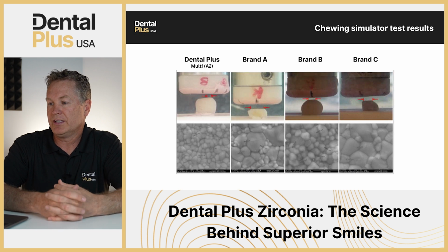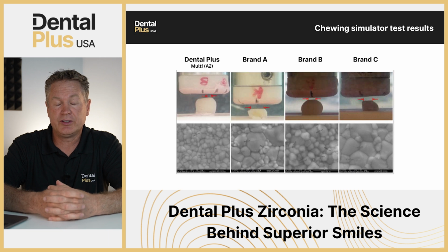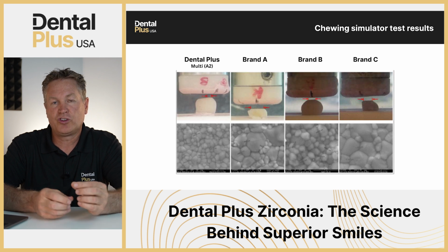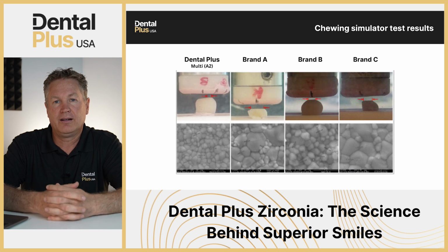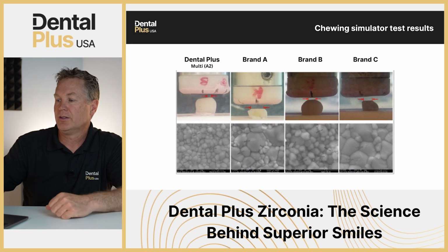So you'll notice in this slide, you can see the difference as far as the wear facet that was left. We put our zirconia and three other competitor zirconias, kind of major brands in the industry, and tried to see how much of a wear pattern each creates through the same amount of chewing cycles. The Dental Plus Multi Zirconia created the smallest, least amount of wear on the opposing compared to all the other brands. They were all polished the same and put through the cycle all at the same time to go through the exact amount of cycles. It's just interesting to see the difference, but that's another really great advantage to this zirconia.